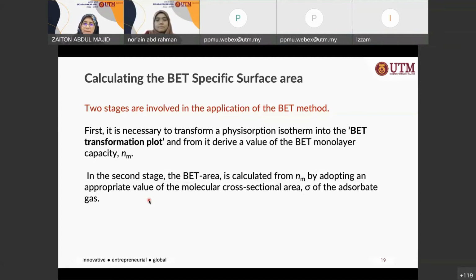This gas adsorption isotherm will have to be transformed into the BET transformation plot. Just the adsorption isotherm is not enough for you to determine the BET surface area. You have to transform it into the BET transformation plot, and all of this, of course, is done by the software. You get many pages of data if you run the multi-point analysis. And from that, you get the value of the BET monolayer capacity, nm. In the second stage, the BET area is calculated from nm or from Vm by adopting an appropriate value of the molecular cross-sectional area, sigma, of the adsorbate gas.